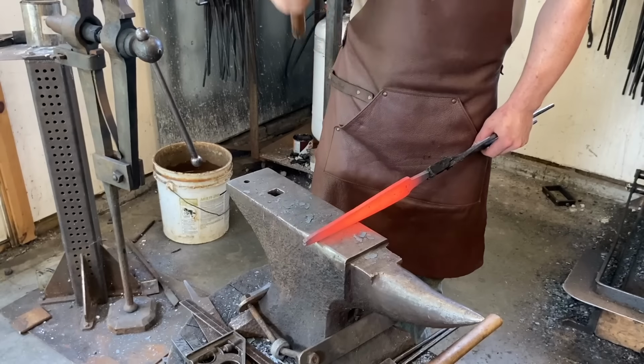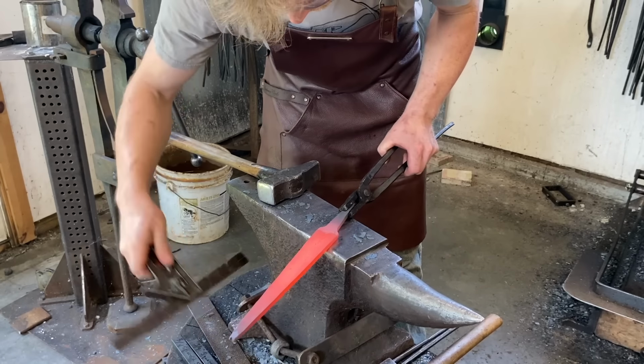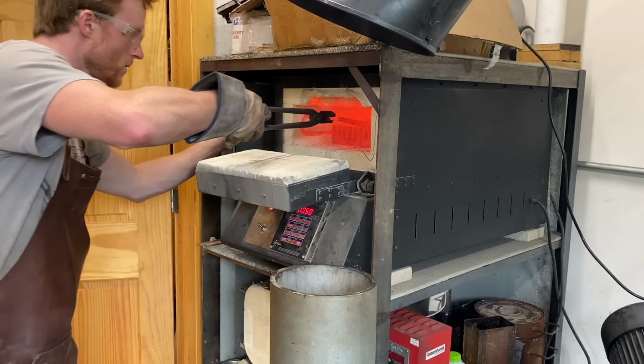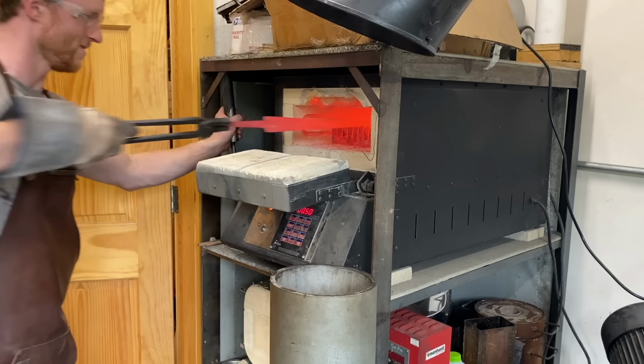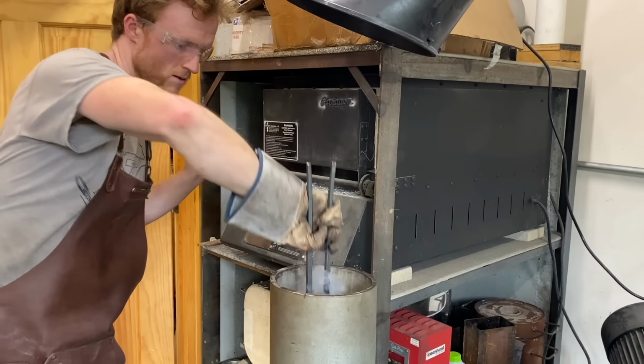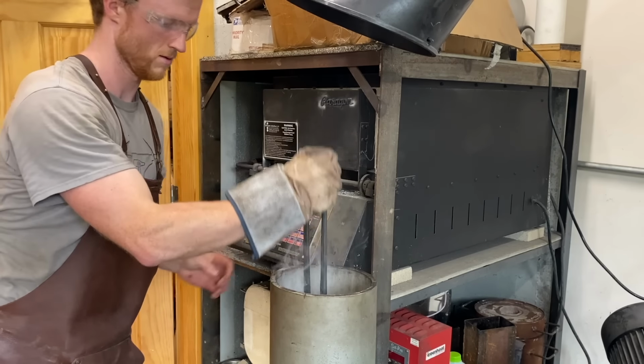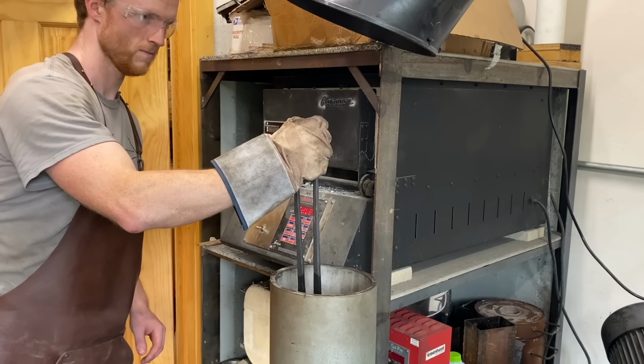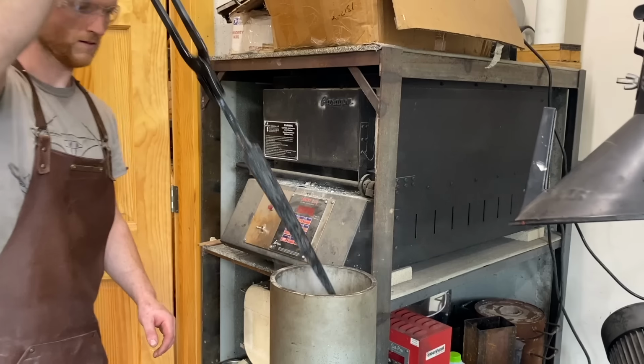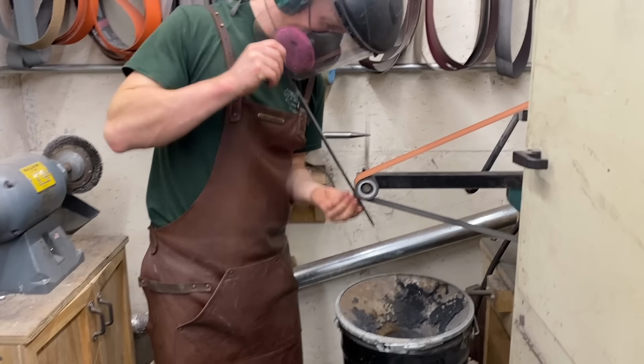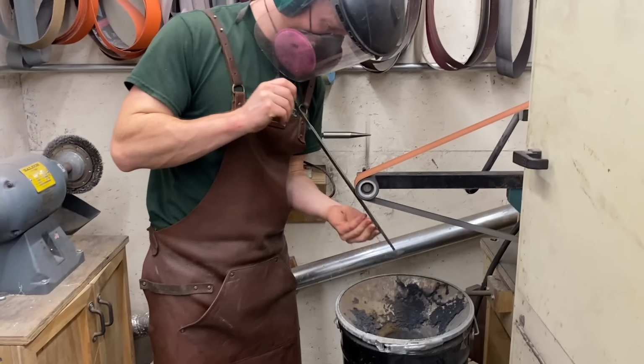Once the blade is forged to shape, it's time to heat treat it. I harden the blade by heating it at 1475 degrees in my heat treating kiln and quenching it in oil. Once the blade is fully cooled down, then I'll put it in the oven again at 425 degrees for a tempering operation. And then it's time to grind the blade.